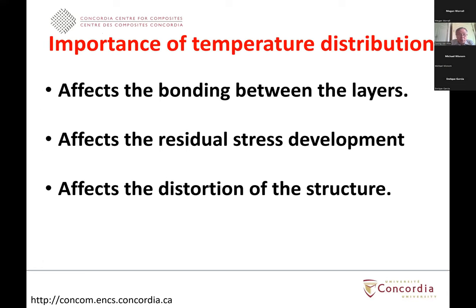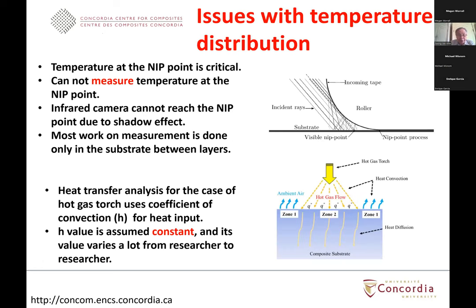In this case, the importance of temperature distribution. What I find in the case of thermoplastic processing is that it's very important to have the bonding between the layers. The layers need to be melted and bonded. If the temperature is not high enough, then the bonding may not be good. The second one is that you also have temperature gradient. The fact that you have heating and cooling during the process means there may be a temperature gradient, and this can create residual stress development. And the residual stress development creates distortion of the structure. So everything really depends on the temperature distribution.